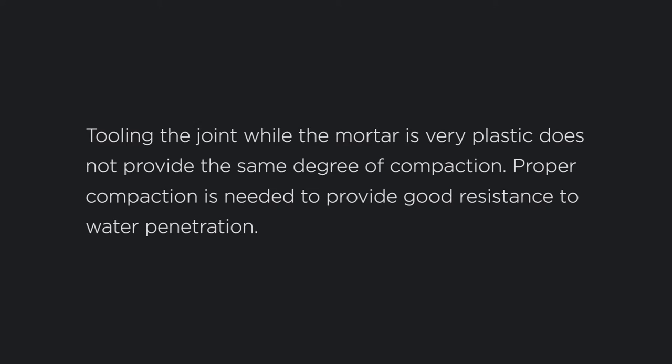Sometimes units are laid almost up to quitting time, and the units are tooled too early. Tooling the joint while the mortar is very plastic does not provide the same degree of compaction. Proper compaction is needed to provide good resistance to water penetration. Joints that were tooled early often have multiple ridges on the surface of the mortar parallel to the direction of the tool. Ridges form as mortar sticks to the tool.